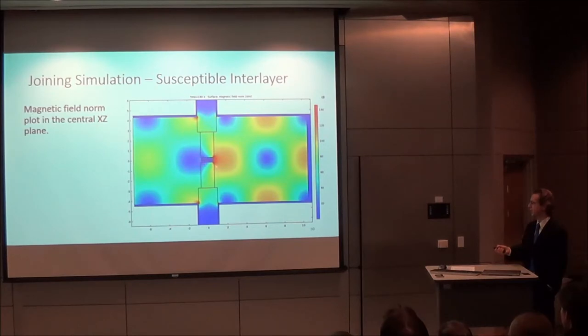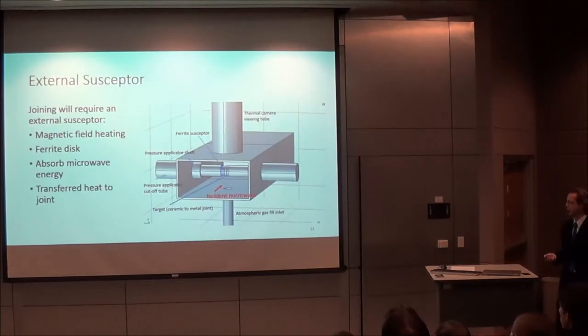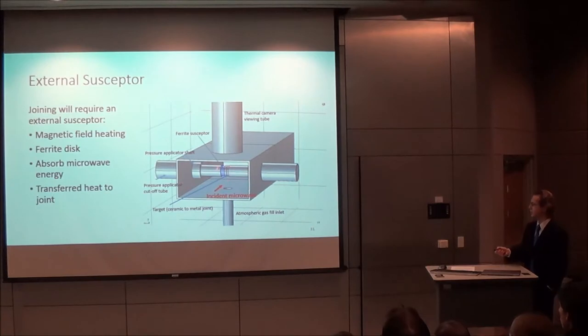And you can observe here that the magnetic field intensity is sufficiently large near the joint itself, that perhaps by placing a magnetic material here, we might couple the wave and generate enough heat that can transfer to the joint to melt the interlayer and join the two materials. And so a new model was produced, and this uses a ferrite susceptor. This is where the ferrite comes in that I talked about before. And so this will heat via the magnetic hysteresis mechanism. It'll absorb microwave energy directly and then transfer that heat to the joint.